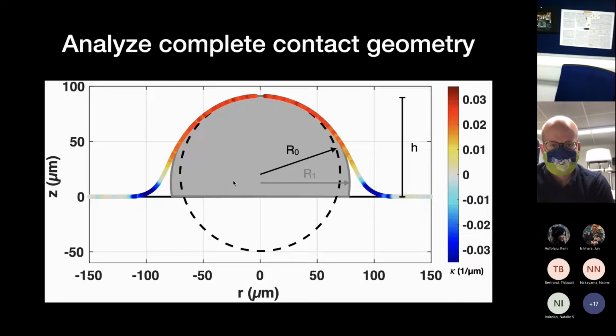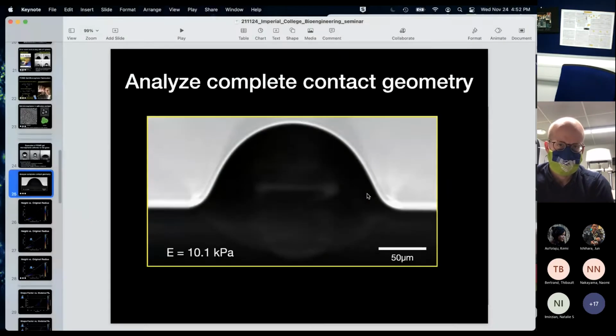In this case, there's a solid under here that can sustain a stress. But in the liquid region, which is approximately here, it's probably not quite. This probably isn't quite as sharp as we've extrapolated it. And we always see a negative curvature. So this shows us that this is the liquid foot region and that it's under a tensile pressure. I guess that tells us a little about what's happening there. But I do think it's always there.